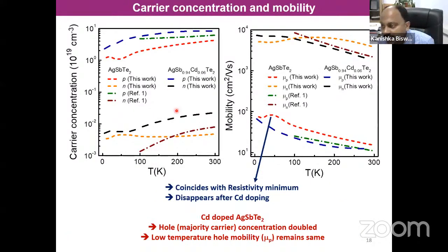So then we have measured the mobility, and this compound is semi-metallic. It has both holes and electrons, but the hole concentration is much higher, around 10 to the power 19, while the electron concentration is 10 to the power 17. So this is a hole doped sample, as I told you, cadmium 2 plus doped in the antimony position. As soon as I dope cadmium, the hole concentration doubles in this sample, but the mobility remains the same in the low temperature region, even in the room temperature region. So we don't see a decrease in mobility, although the hole concentration doubles. That happens basically due to delocalization of the electronic states, and this delocalization actually enhances the electronic transport in this material.